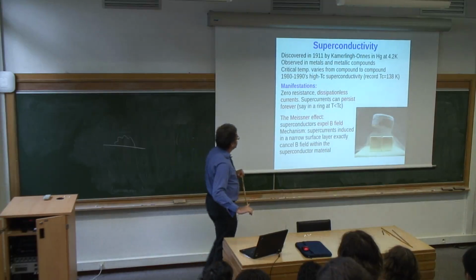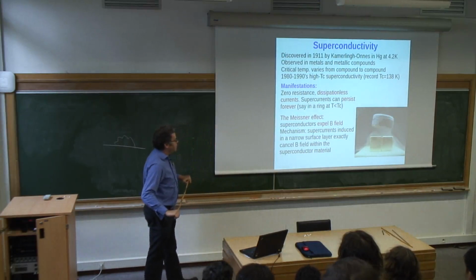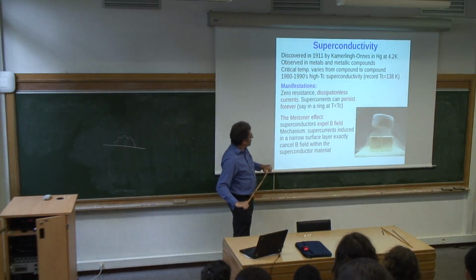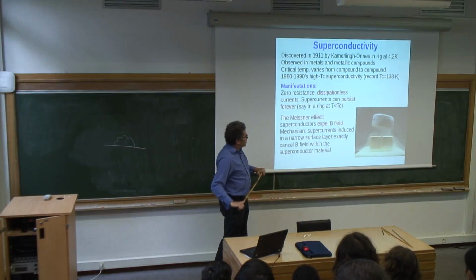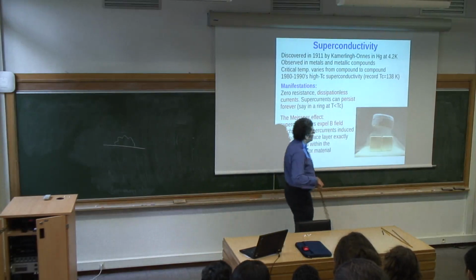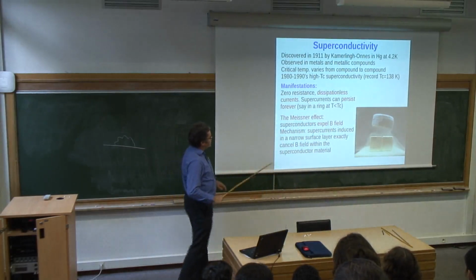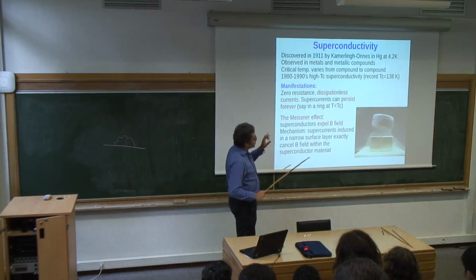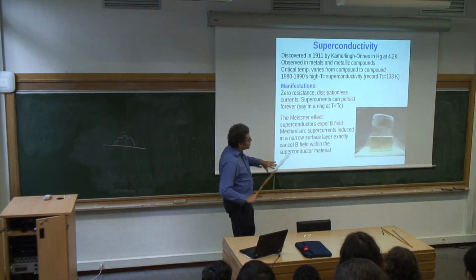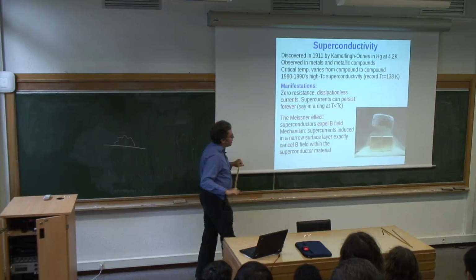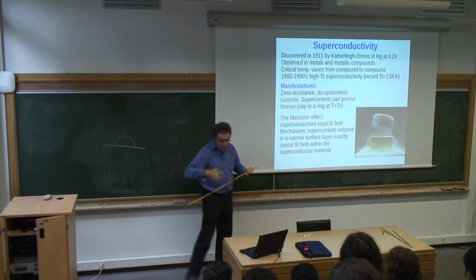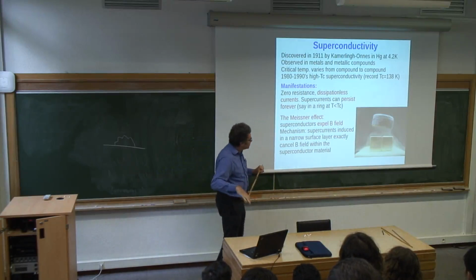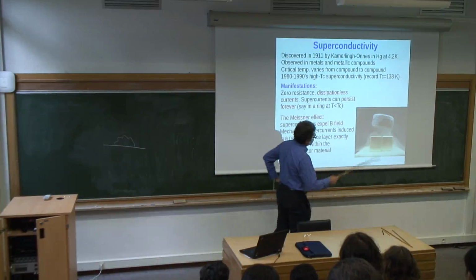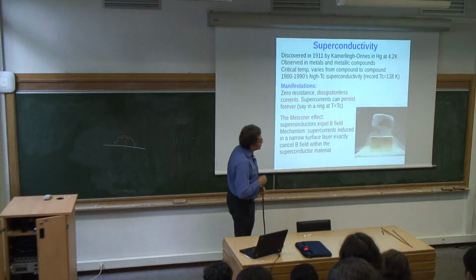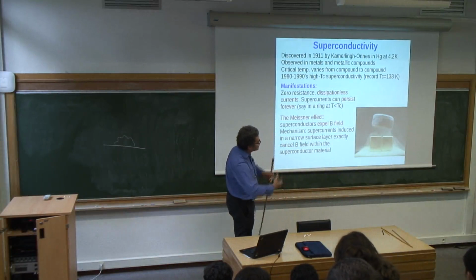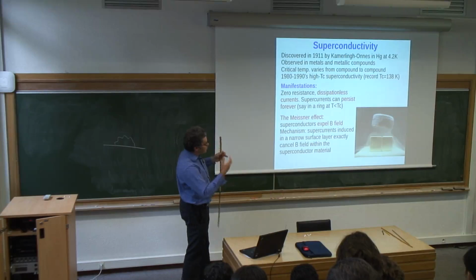And also there are striking effects like the Meissner effect, that a superconductor expels magnetic field, and because of that it can be suspended in magnetic field and levitate above a magnet. And the mechanism for that is that in magnetic field there are supercurrents which are induced in a thin layer near the superconductor surface, and these currents shield the magnetic field from the outside, and it becomes zero inside, and so the superconductor becomes a perfect diamagnet, and as a perfect diamagnet expelling magnetic field, it will repel from the outer magnetic field and levitate.